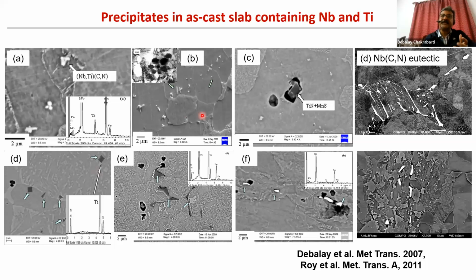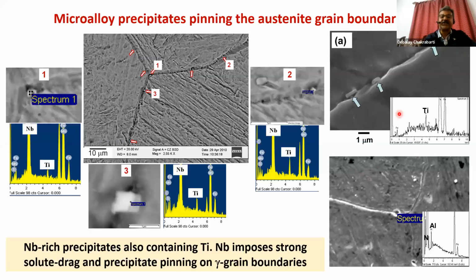And because of segregation, the precipitate size can be many times higher than what is expected considering nominal composition. Because if in a certain region niobium is segregating, naturally the precipitates that form will grow into large size, and those precipitates can even reach several micrometer size and form something called eutectic compounds at some locations. And if this kind of hard particles are present, then this can be really detrimental to properties like toughness, as they help in crack initiation.